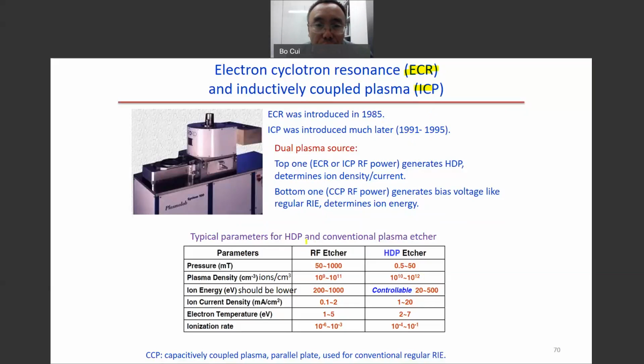So here is the comparison between the regular RIE process and the high density plasma etcher. First, for the high density plasma etching, as we have seen, because the ionization is very efficient, we can have lower pressure. But for the RIE, we need, not necessarily 50, maybe 10 millitorr. 10 millitorr may be okay, but not much lower than that. But for the HDP, we can go to even half a millitorr. The plasma density, you can see, is 1 to 2 orders higher for the HDP etcher. So for the ion energy, we can have lower ion energy by using lower bias power.